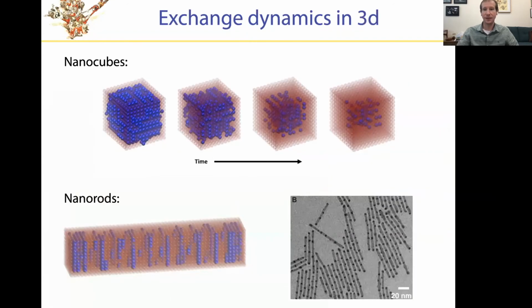All right. We see very similar behavior in 3 dimensions. For nanocubes, you can see as this thing proceeds, again, the emergence of this modulated structure and these exotic structures transiently as exchange proceeds. There's also very interesting shape dependence. This was a little movie of a nanorod at intermediate composition. And now a consequence of those elastic interactions has been to form a natural spacing that you might be able to detect with your eyes here between domains that are rich in one material or the other, and very much akin to what's been observed in experiments.